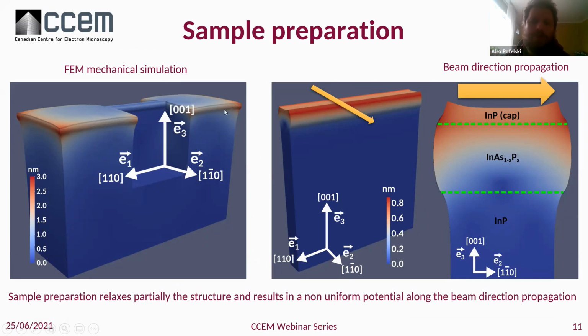Then here, it was just a cut to see what was happening on the window region. As you can see, the scale is now different because the deformation on this window level is slightly lower. What was interesting to see is that there was no deformation along the 110 direction. So the pillars on each side were maintaining the structure. This was then used to change from this 3D problem to this 2D problem, because the problem of this finite element mechanical simulation is the meshing. The density of the mesh was absolutely huge on that one, I think something like 1 million nodes. And even then, those nodes were not properly mapping the strain into the stress layer. So we found a way to simplify the geometry to have a better description of the strain relaxation phenomenon.